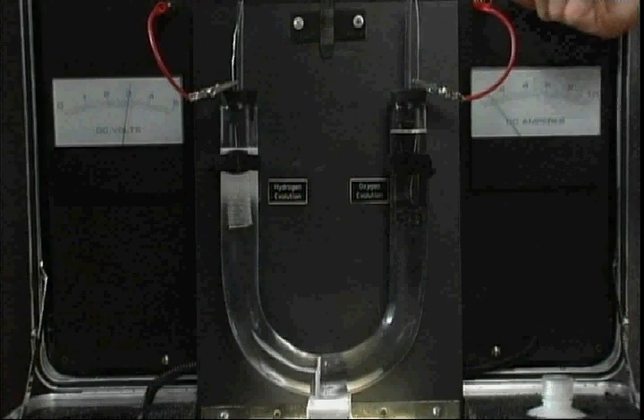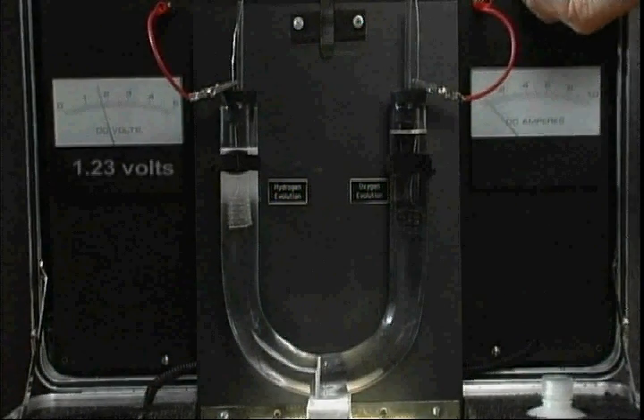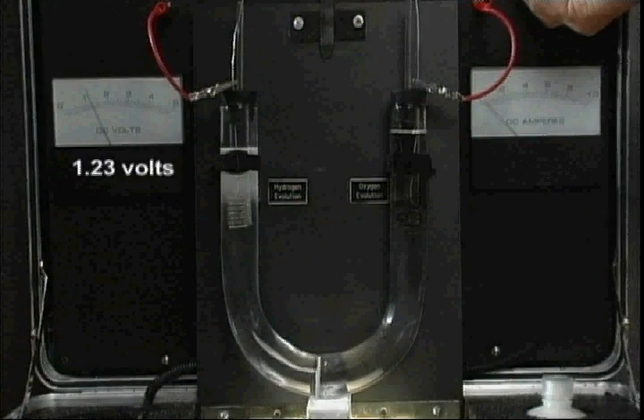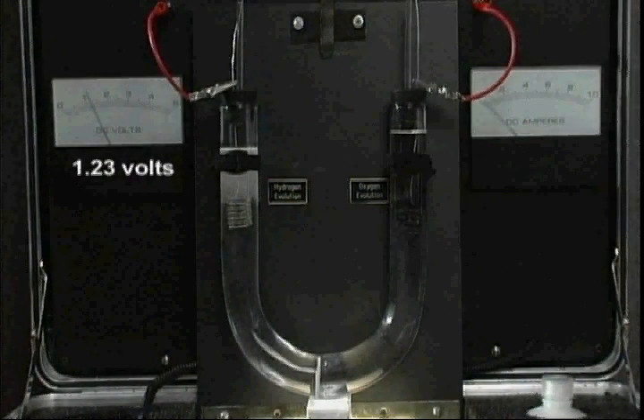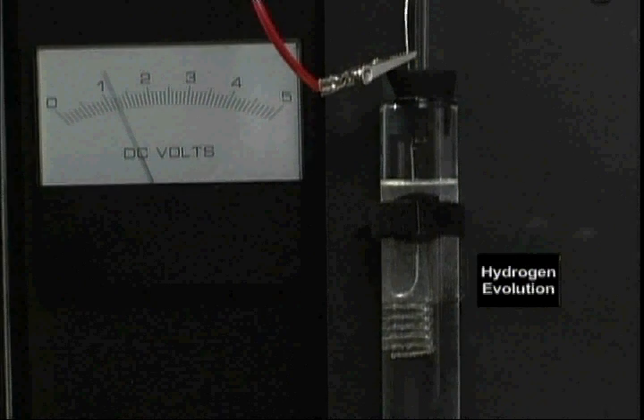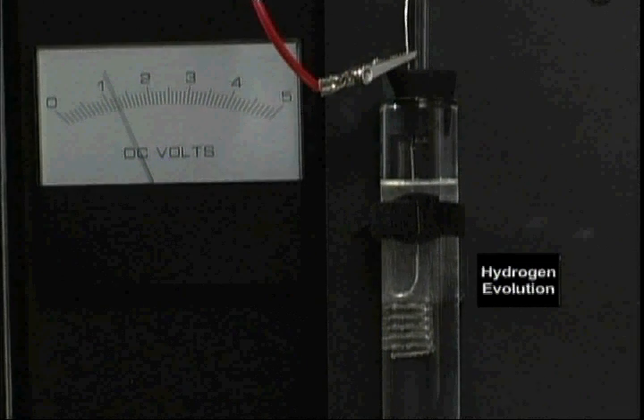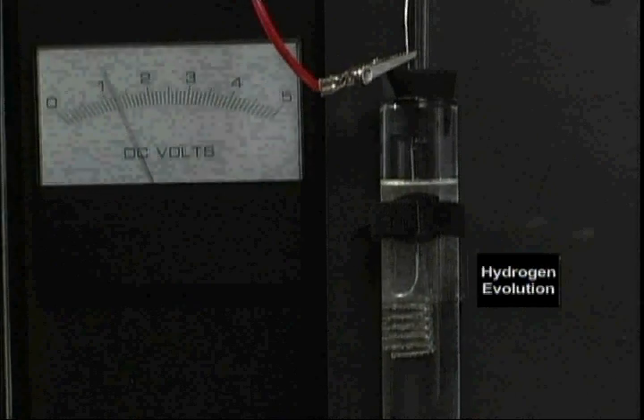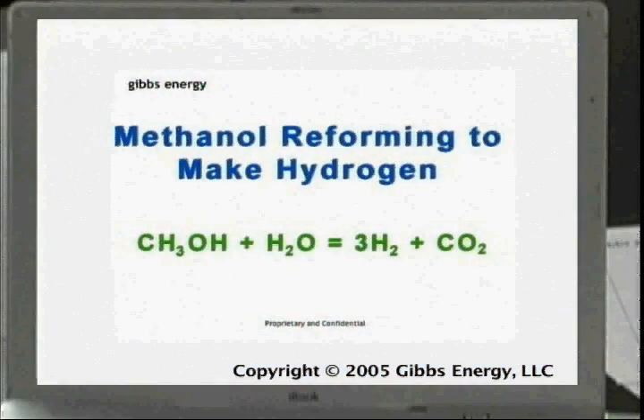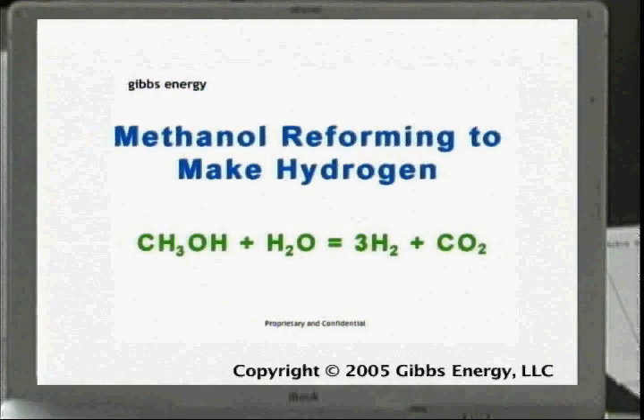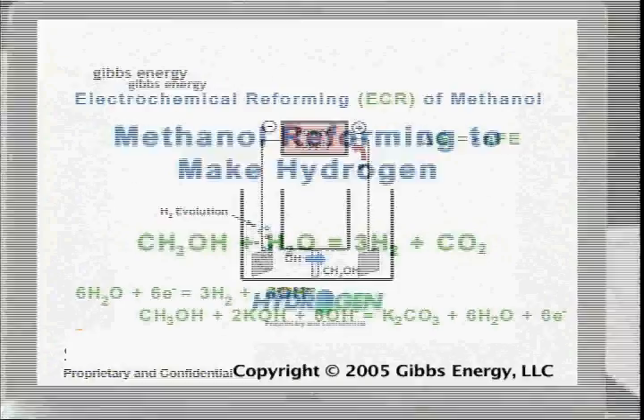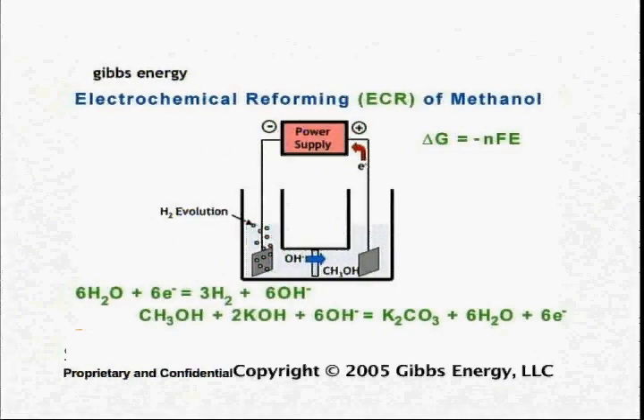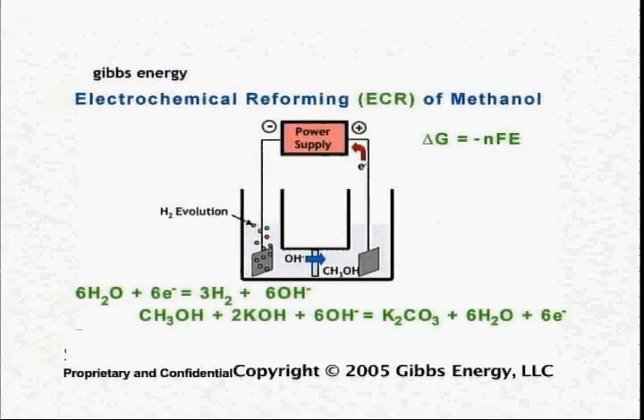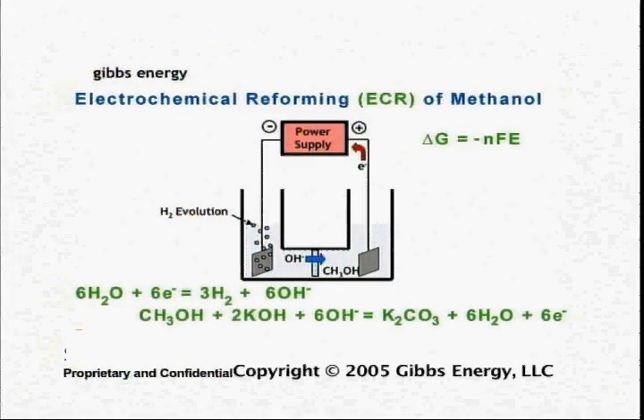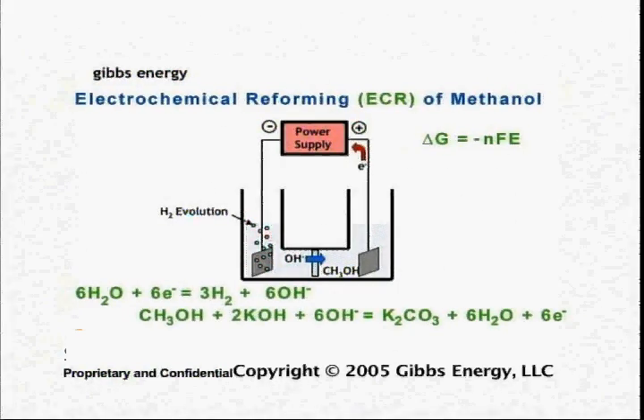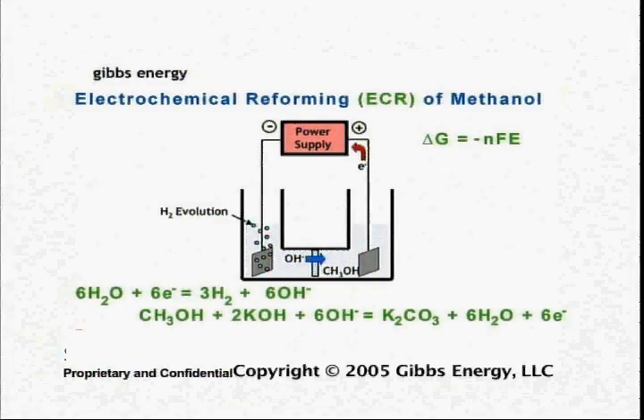If we reduce the voltage to about 1 volt, we continue to see hydrogen evolution. This is well below the theoretical 1.23 volts for water electrolysis. Again, this lower voltage is evidence that we are not electrolyzing water and that the mechanism at this electrode has changed. Theoretically, the methanol reaction should actually occur with zero net voltage input. However, like oxygen evolution, methanol oxidation is kinetically slow. Hence, some additional or excess voltage is consumed as internal resistance in the electrolyte and to activate the methanol electrode.